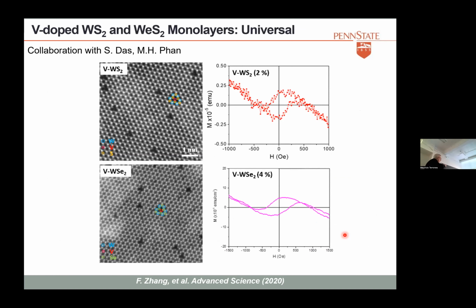He did the same set of vanadium concentrations, similar ones, and we could see that the ferromagnetic signal was high when, in this case, it was 4%. You can see the average vanadium distance was sort of similar, and as we put more vanadium, that ferromagnetic signal was dying out. The fact that when we put more vanadium we couldn't see any ferromagnetic signal was very interesting, because you could see it's coming and it's going.